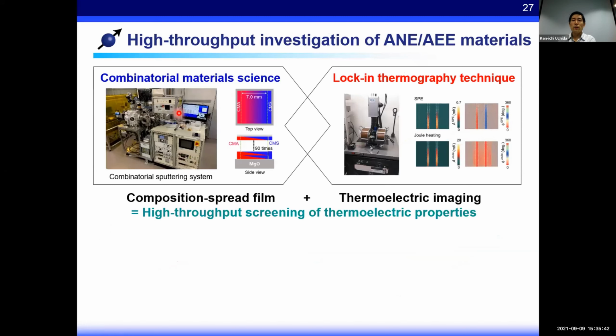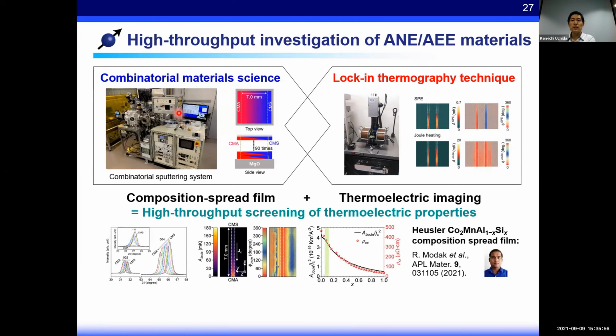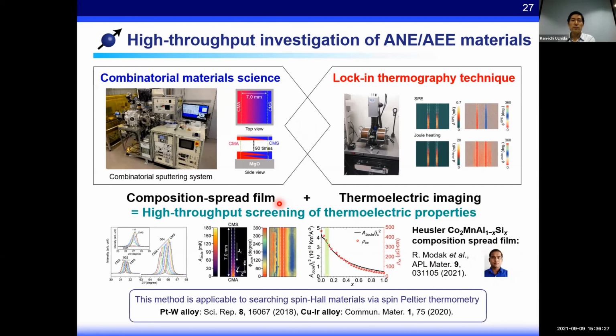To accelerate the material searching, we have recently developed a high-throughput screening method for the thermoelectric and thermospin conversion phenomena, combining a lock-in thermography technique with combinatorial material science. By visualizing the temperature distribution modulation in the composition spread film, we can obtain the systematic and continuous composition dependence of the anomalous Ettingshausen effect from a single sample. Dr. Modak, one of the members in our group, has demonstrated the usability of this method by forming the epitaxial Heusler alloy film with a composition gradient. Importantly, this method is also applicable to searching for materials with high spin-to-charge conversion efficiency by measuring the spin Peltier effect. Therefore, this high-throughput screening method will accelerate the materials research on the interconversion between the charge, heat, and spin currents.